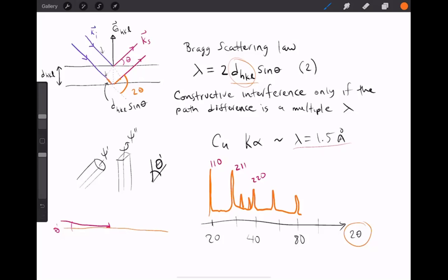So let's say you were making platinum, you have platinum crystals that you put in there, right? Maybe your platinum crystals have a small discrepancy in the unit cell size of your system compared to the one that is in the database. So that could be the reason for the shift, that you're shifted by 1% because your unit cell is off by 1%. Oh, I see. And it could be off by 1% on average because you have impurities in the materials that you were growing with.